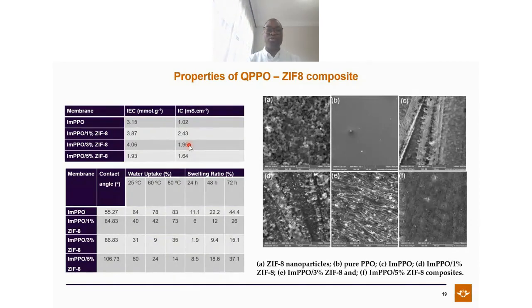Oh, this was interesting. Wanted to see how this would perform. Also, we continue doing different types of analysis. If you look at the same analysis, you can see this is the ZIF and this is the one without ZIF. The moment you start putting ZIF on the material, it starts showing a different pathway on the surface because it's showing harsher conditions. The moment you start seeing these spots and also these stretches, these are part of the pathway which is able to transport the OH minus of the ZIF.